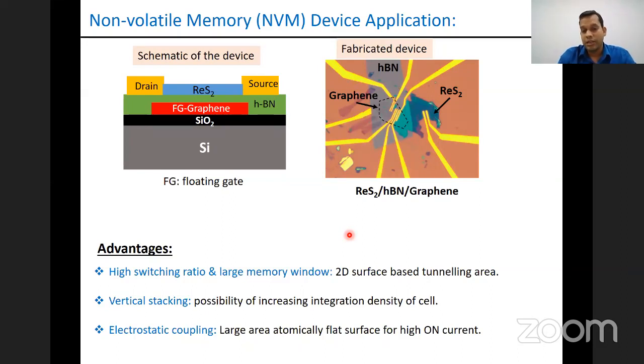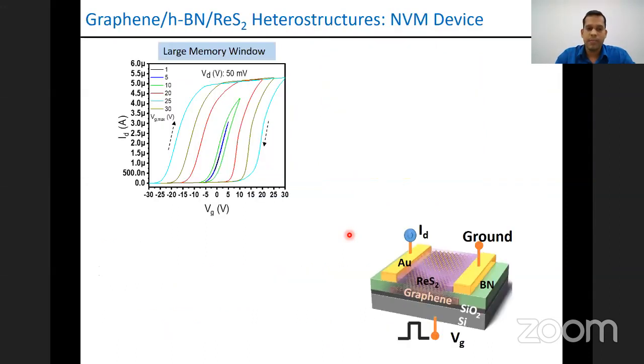So it has a very large tunnel area, and it can show a high switching ratio and also a large memory window. As it is a vertical stack, there is a possibility to increase the integration density of the cell. And of course, the electrostatic coupling can be enhanced hugely due to the 2D large area. What we initially observed is that if we sweep the gate bias, then we see huge hysteresis in the drain current, as shown here.